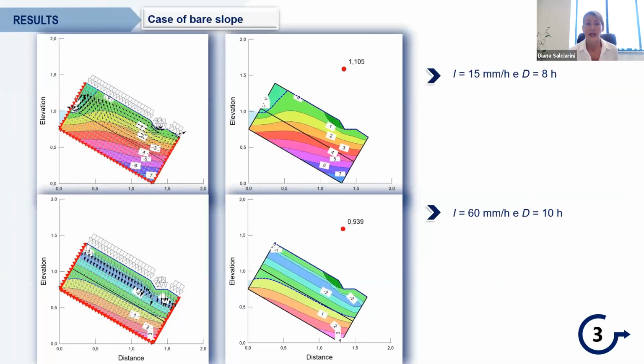Coming to the results, as for the bare slope, we tested the numerical model with the two rainfall patterns. We obtained a stable condition for the low rate rainfall, and an unstable condition for the high rate rainfall as observed in the experimental test, demonstrated by a safety factor less than 1.